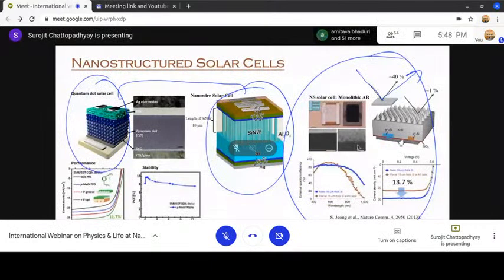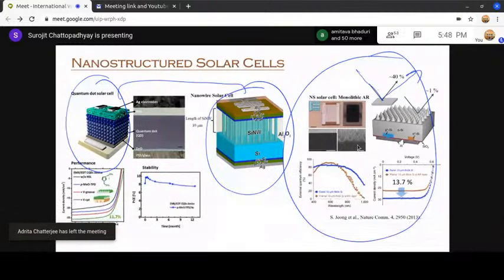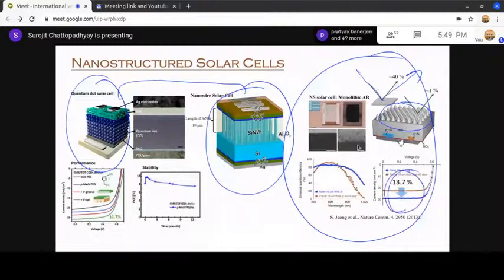If you nanostructure the top of the material, like these nano pyramids, then the reflection can come down to below 1%. And when the absorption of sunlight is more, of course, the current will be more. And you can see from this IV diagram that the current has increased. When you add a monolithic anti-reflection layer, this AR that you see means anti-reflection. So if you make the top of the solar cell like a nanostructure, then the reflection will go down. That means you are getting an anti-reflection effect. So you can pump more sunlight into the device, and you get more current. That's one more application of nanomaterials.